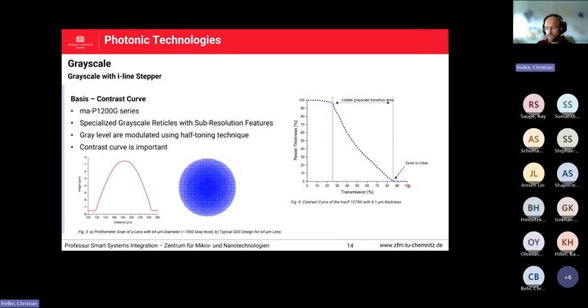So 100% transmission, meaning the whole mask is empty, no chromium layer is there, so all of the light goes through. So if we expose with 400 microjoule per square centimeter, for example, 100% transmission means 400 microjoule per square centimeter. 50% transmission, for example, means then 200 microjoule per square centimeter, but that cannot be tuned within the process itself, but with the mask substrate, for example.